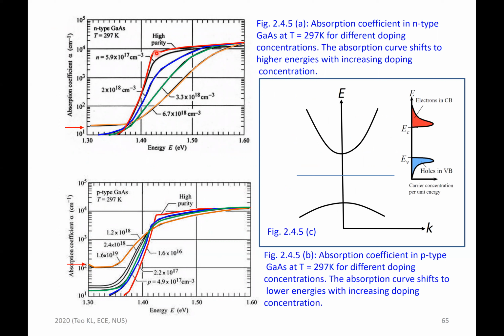Next, you can see that as the concentration increases, all the absorption curves actually shift to higher photon energy. This is due to the Burstein-Moss shift. And you can see for each absorption curve, the blue, the green, and also the orange, there is this exponential decay of the absorption coefficient. This is due to the band tailing effect, which is the formation of tail states.